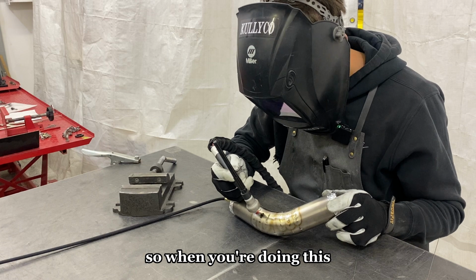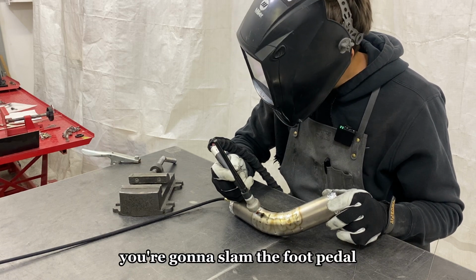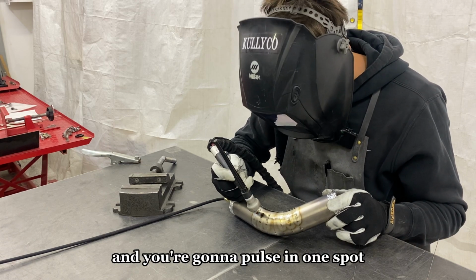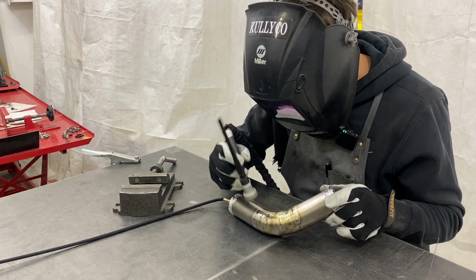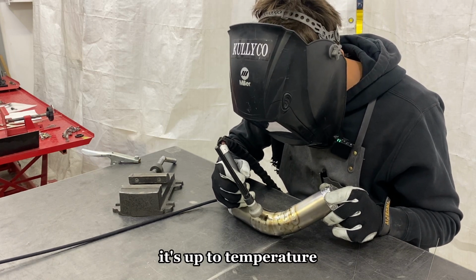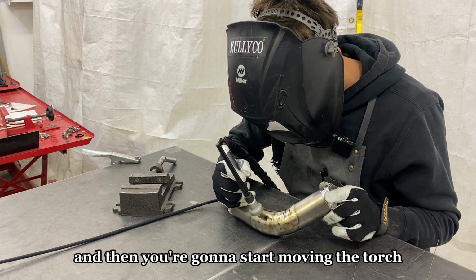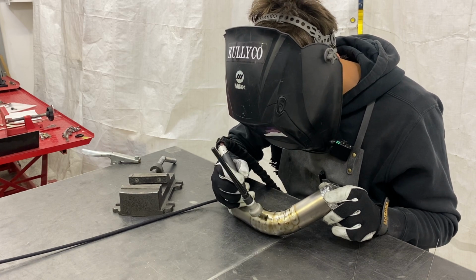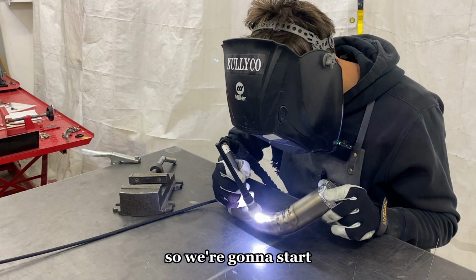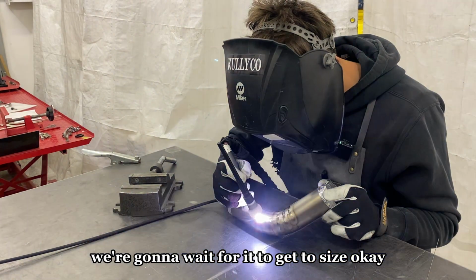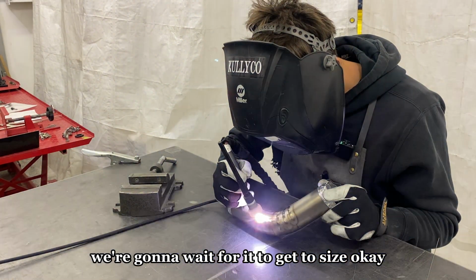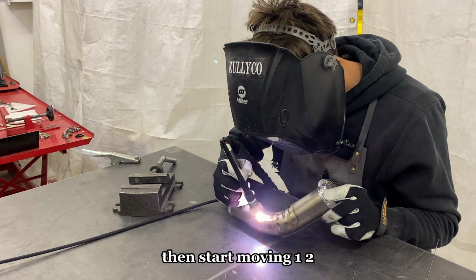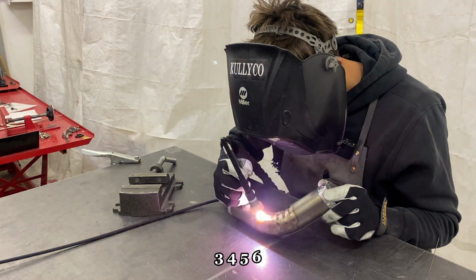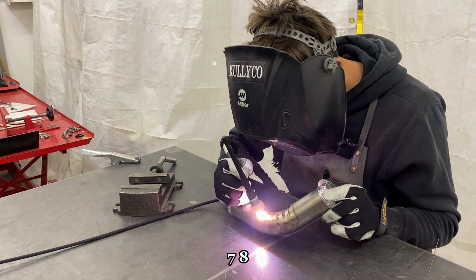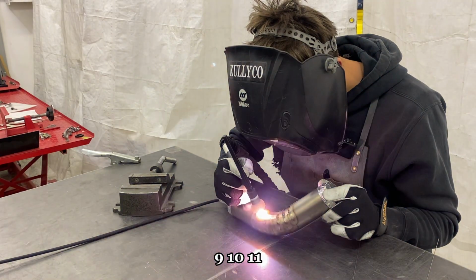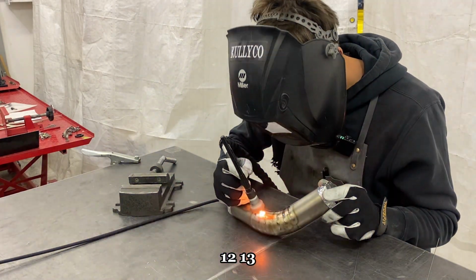So when you're doing this, you're going to slam the foot pedal and you're going to pulse in one spot until that puddle is the width that you're looking for. It's up to temperature, and then you're going to start moving the torch with every pulse. So we're going to start. We're going to wait for it to get to size. Okay, then start moving. 1, 2, 3, 4, 5, 6, 7, 8, 9, 10, 11, 12, 13.